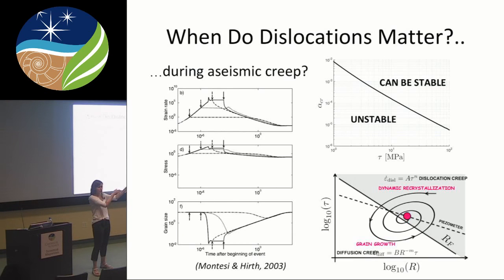those weak zones on Earth could be preserved because the temperature is low enough and grain growth is slow. If you had a similar process on Venus, which is a similar sized planet, the weak zones would heal a lot faster. So by the time you can form an interconnected set of weak zones that could potentially form a plate, they don't form as easily on Venus because they heal too fast.